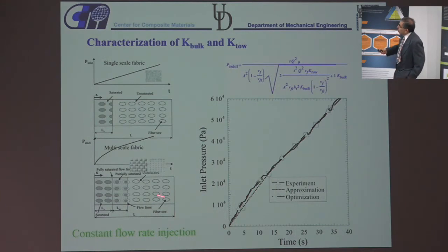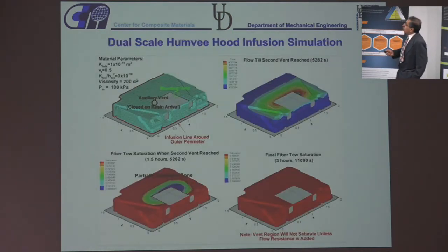Now usually the bulk permeability is the slope very close at the inlet, so this value you can find immediately, and then you keep changing the tow permeability until they match. And so from one experiment you can get both the values of the bulk and the tow permeability. And then you can apply this methodology to, we did a simulation of the hood where you inject on the dual scale, and you find that this is the region that is partially filled when the resin reaches the second vent, and that is after an hour and a half.